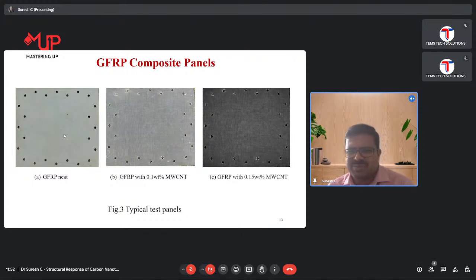So we have considered 0.1 weight percentage of multi-walled carbon nanotubes and 0.15 weight percentage of carbon nanotubes. By seeing the color of the composites, you can see when we increase the amount of carbon nanotubes, the structure color is changing towards black, because carbon's color is naturally black. So we considered three types of structure. First one is GFRP neat, where no carbon nanofillers are used, and the second structure is GFRP with 0.1 weight percentage of carbon nanotubes.